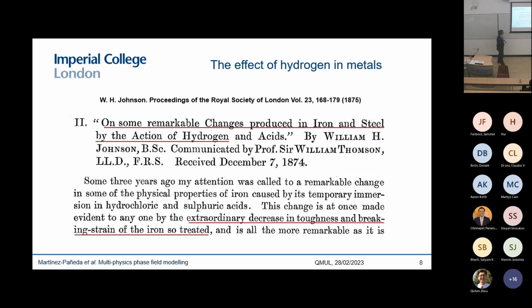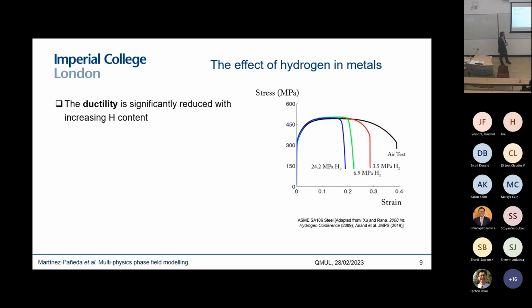So this is a paper from Johnson written in the Proceedings of the Royal Society back in 1875. And you can see that he speaks about some remarkable and extraordinary decrease in toughness and breaking strain in iron and steel in the presence of hydrogen. And in those days, you will very rarely see words such as extraordinary or remarkable in scientific papers. But the way the hydrogen interacts with metals is indeed quite remarkable and extraordinary. So one of these effects, for example, is how hydrogen significantly reduces the ductility of metals.